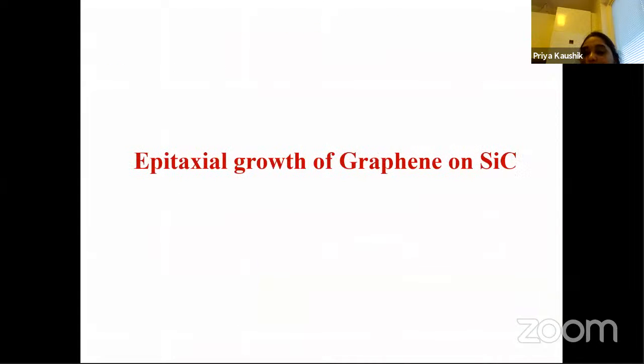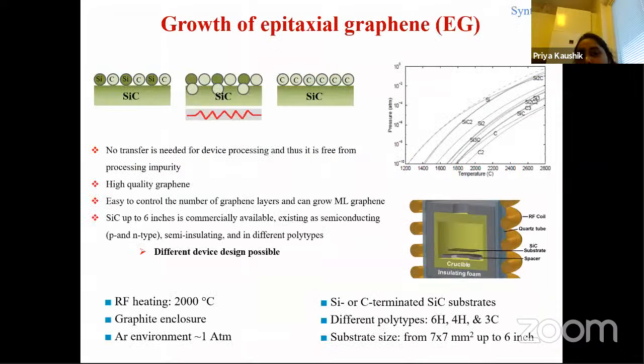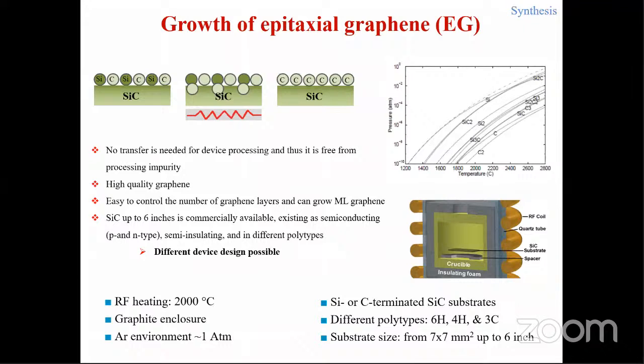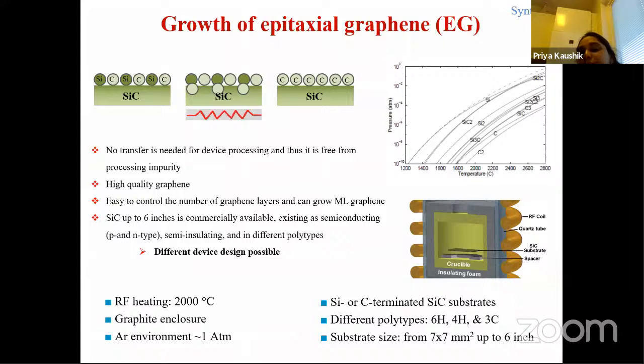In our lab, we grow graphene on silicon carbide by sublimation epitaxy, and Mikhail has already introduced and gave a glimpse of how we grow graphene on it. I just want to cover a brief of it. We have silicon carbide as a substrate, and the substrate contains both silicon and carbon atoms. When we heat it to around 2000 degrees Celsius, the silicon atoms sublime and the remaining carbon atoms form the graphene on silicon carbide.